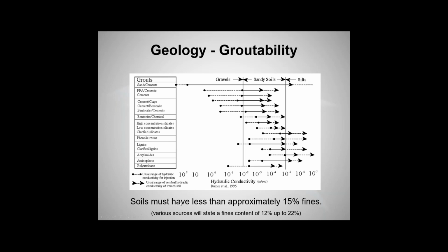So I have a note down here, and the fines content of the soil is very important. As you can see, the rule of thumb that I typically use is that soils must be less than approximately 15% fines to be groutable. That's going to vary, I think, depending on the exact grain size and soil type and things of that nature.